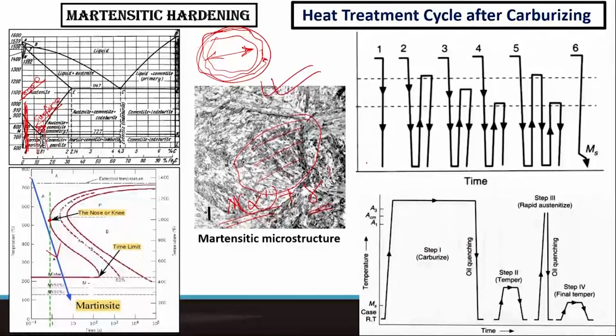And we necessarily have to go to the austenitic region, because austenite has the highest carbon dissolution or absorption capacity. So carbon solubility is about 2.11% when it is in the austenite region. Compared to that, the ferrite has only 0.025 or less. So it is for these two reasons. One, the carbon diffusion rate is higher because temperature is higher, so we have to go to the austenitic region. And number two is that the capacity to dissolve carbon is much higher in the austenitic region.